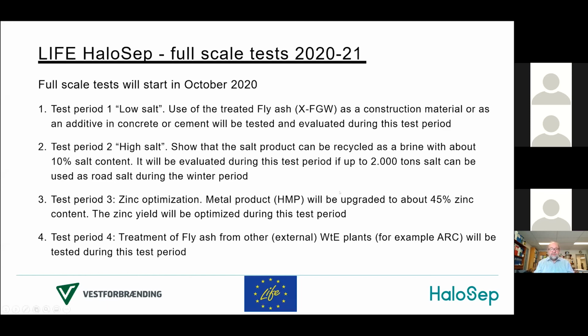Test period 2 is what we call high salt. We will show that the salt product can be recycled as a brine with about 10% salt content, so no evaporation here. It will be evaluated during this test period if up to 2,000 tons of salt can be used as road salt during the winter period.